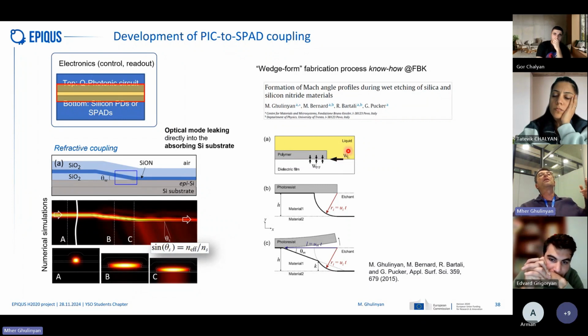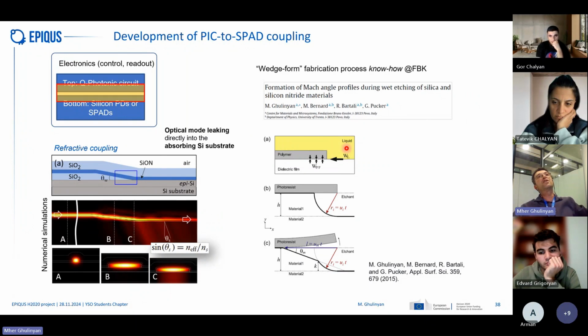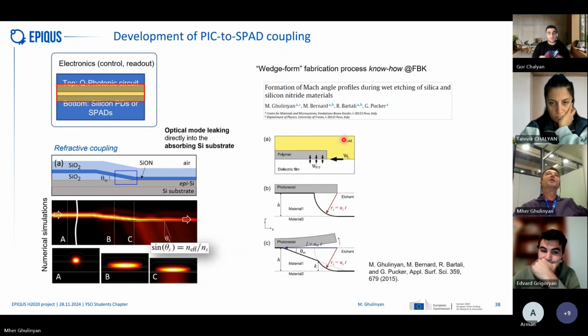So what happens if you put metal inside a corrosive acid, okay, your metal will start to corrode and dissolve. So this is etching, and in an acid, in a liquid, it is chemical etching. The liquid reacts with your material, and layer by layer it removes your material. This is called isotropic etching, and it goes in all directions at the same velocity, dissolving your material. While anisotropic etching is very directional, and it is bombarding your material. That also creates a very rough surface on the unprotected part of your material.